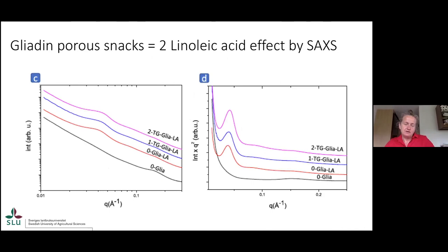We move on to another additive, a very interesting linoleic acid effect we wanted to show in the samples. But the idea to introduce this additive was to increase the nutritional value of the snacks. Actually, the scattering curves show that only gliadin, no additive, has a rather simple scattering pattern. While with additives, there are barely differences between the no enzyme and enzyme containing samples. Again, if you look at the scattering pattern on the right, a very clear linoleic acid pattern shows that linoleic acid is not incorporated in the protein network and is actually sitting as a component in the structure.